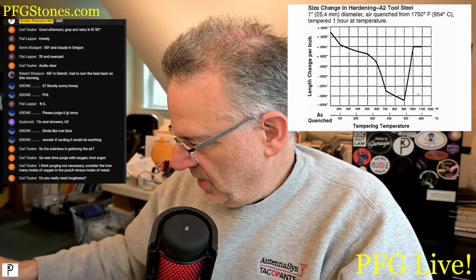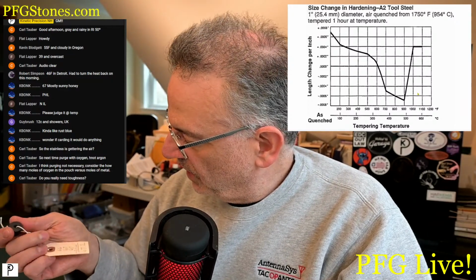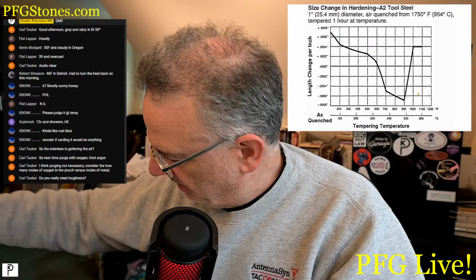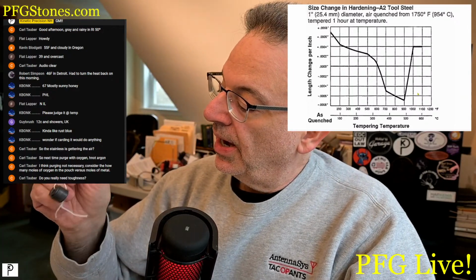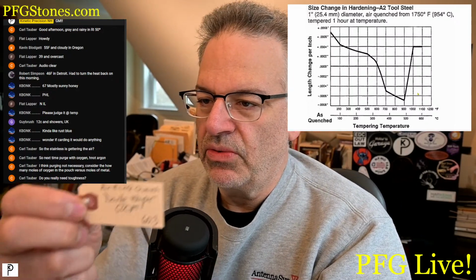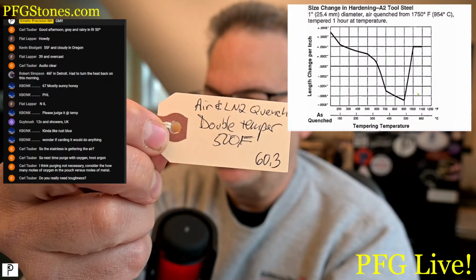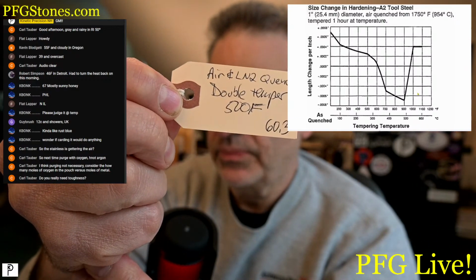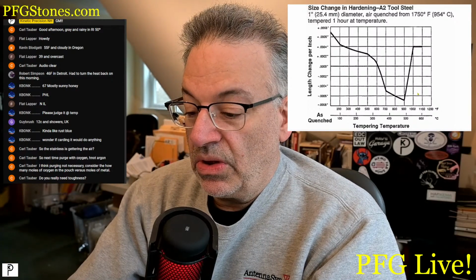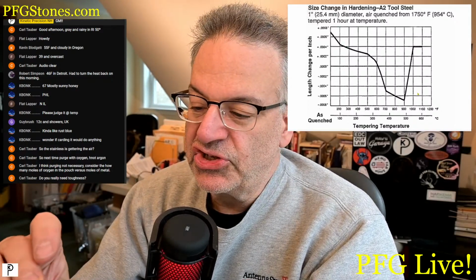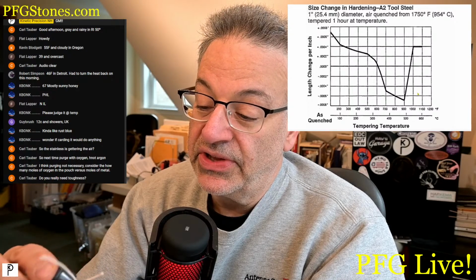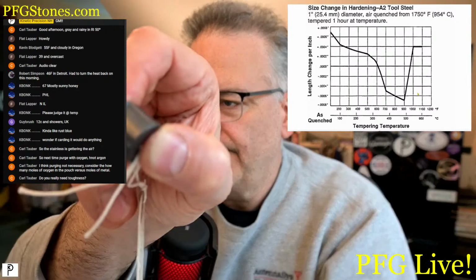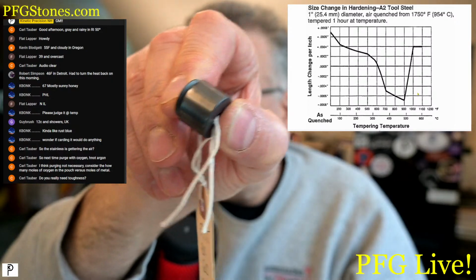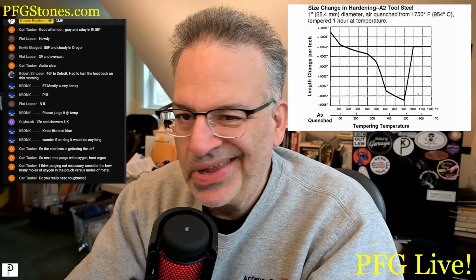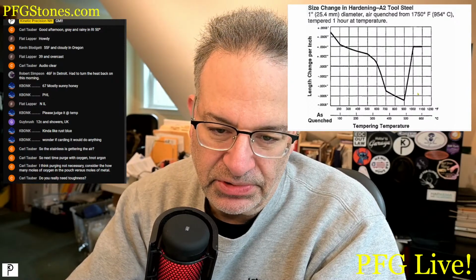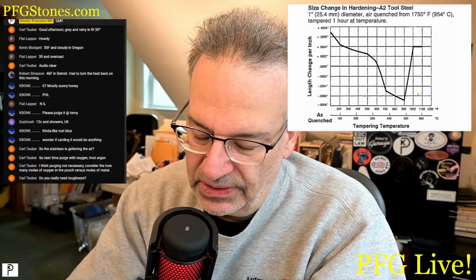I took one of the parts, the one that went through. Let's see, my sample parts. Here it is. I took one of my parts, which went through the entire double temper. Okay, and I measured the diameter, and then I stoned off the oxidation from one side. Let's see if you can see that. Okay, and then I measured it again. It was essentially unmeasurable. So the oxidation wasn't the issue.